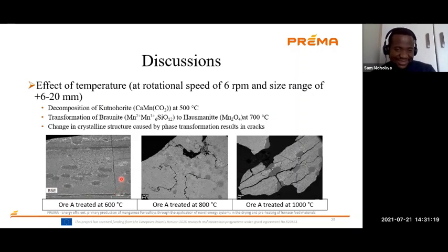Here we have Ore A that is being treated at 600. You remember that this transformation happens at 700. So that is why here you see that there aren't many cracks, because there's barely a transformation of Braunite into Hausmannite, which causes cracks. Here at 800, you have more of this Braunite transforming into Hausmannite. That's why you can see that there's a slightly larger number of cracks due to this transformation. Then when you go to 1000, you can see that the cracks are even more, because the transformation of Braunite had intensified.